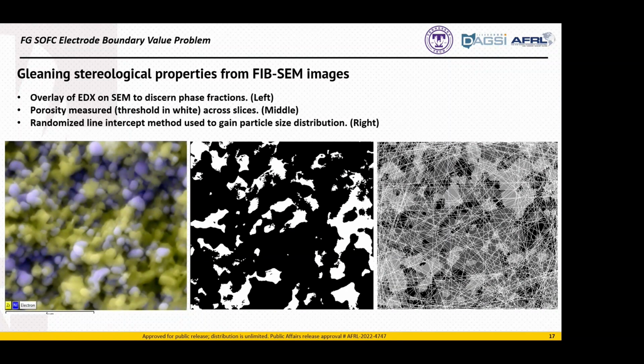we done three-dimensional tomography. So here you have on the left-hand side EDX overlay on SEM showing us the phase fractions in an anode, the nickel and the YSZ. And then we can also pull out the measure of the porosity within the electrode. And then we use a randomized line intercept method to get the particle size distribution of the